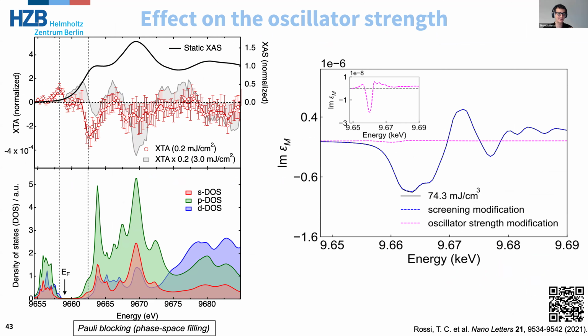The main difference is that we can start to see a positive signal below the edge that corresponds to where the top of the valence band is supposed to be, and an additional negative signal here where the bottom of the conduction band is supposed to be. So now we start to see the Pauli blocking that's negligible when you do the experiment below the Mott density. The problem is, I think there are plenty of more suitable techniques to look at the Pauli blocking than pump-probe XAS, but still here you are observing a signal that displays both the Coulomb screening and the Pauli blocking with nearly equivalent amplitudes. Okay, yes. Gotcha. Awesome. Thank you so much. You're welcome.